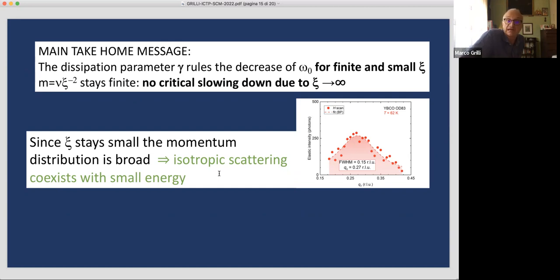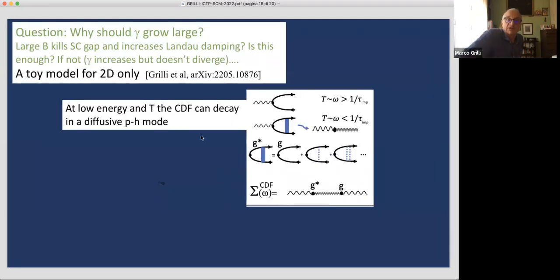So the question is now why gamma should become large. One possibility is simply that if you switch on, for instance, a magnetic field, then the superconducting gap is killed. And of course, you have many more particle-holes to damp this fluctuation. So the Landau damping naturally increases when you kill superconductivity. But the point is that if you want the linear resistivity to go down to the lowest and lowest temperatures, then we need a larger and larger gamma, if this is the good idea. And therefore, we need a diverging gamma. And therefore, just having the closing of the superconducting gap is not enough.